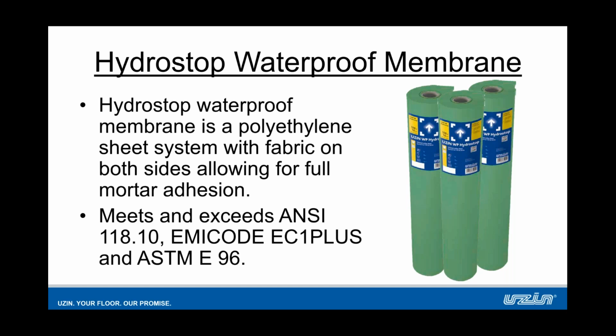ASTM E96, we've got a perm rating of 0.05, and that test, that ASTM E96, is measuring a material's permeance value under set conditions. So what does that 0.05 mean? Well, anything 0.5 and below can be used for waterproofing in a steam shower application, even commercial steam shower applications, without the need of a secondary waterproof membrane. Okay, so we're well below that benchmark. We're at 0.05. The ANSI 118.10, this is the standard that our industry uses for waterproofing membranes. We're meeting expectations with no fungus growth, with no water penetration with the waterproofness test.